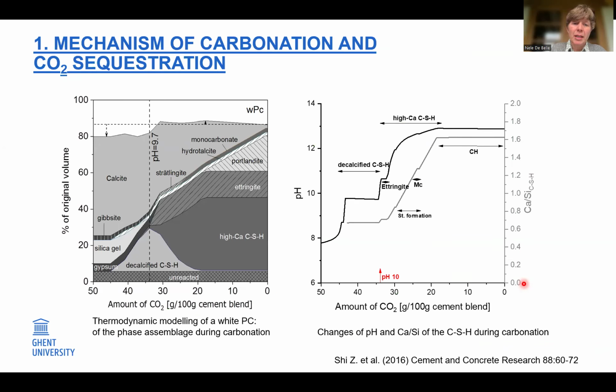Here you can see that the thermodynamic modeling is showing from the right to the left how the phase assemblage of a white Portland cement paste changes as a function of the amount of CO2 that has reacted. And in the right-hand figure, you can see the corresponding decrease of the pH and of the calcium silicon ratio of the CSH. So as you can see here, Portlandite is the first major hydrate that decomposes to calcium carbonate, to calcite. And that leads to a moderate volume increase of about 12%, while the pH is remaining stable around 12.5. Then actually it's the CSH that starts to decalcify down to a calcium silicon ratio of about 1.3.